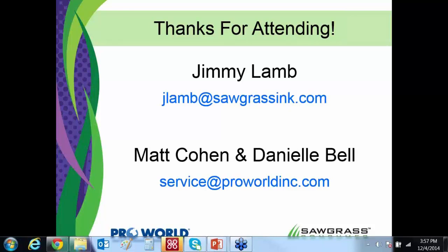The majority of what we're using in this industry, because you're buying manufactured items that were manufactured for sublimation, they do withstand 400 degrees. When you get into the polyester apparel marketplace, polyester apparel typically withstands the 400 degrees as well. The challenges you find with some of the different polyester apparel products is that the manufacturer may have used an additive, for example, an antimicrobial that can interfere with the sublimation gas.